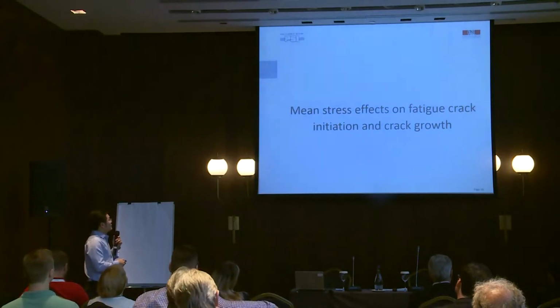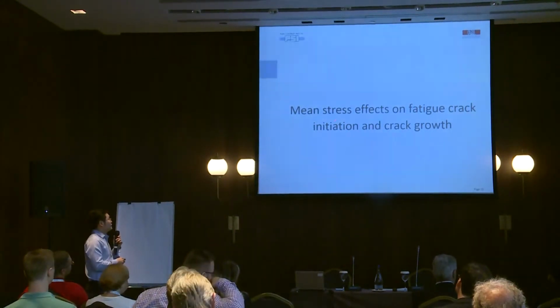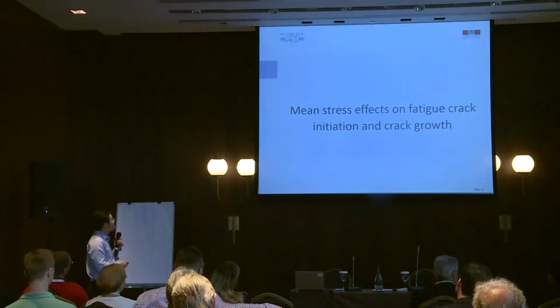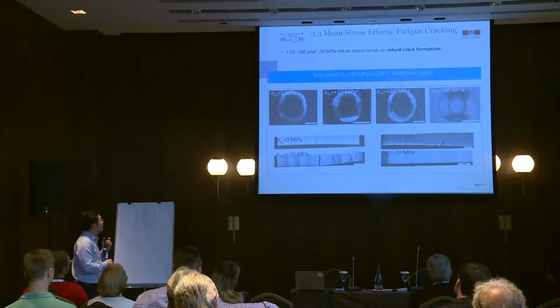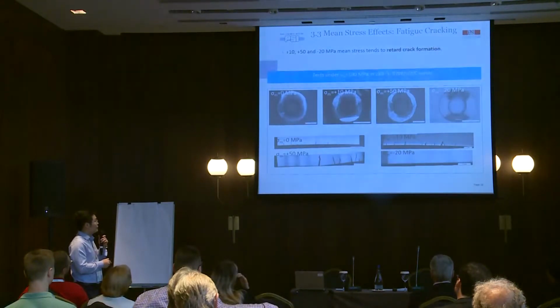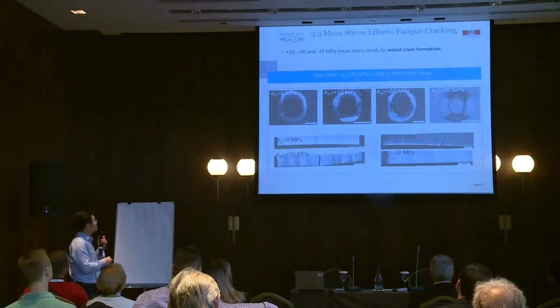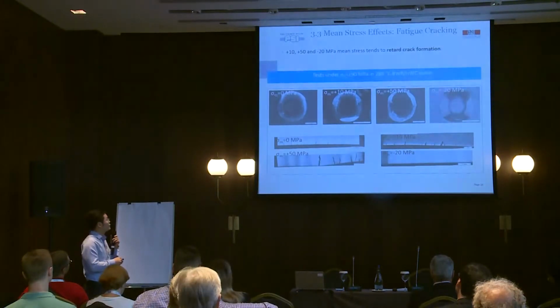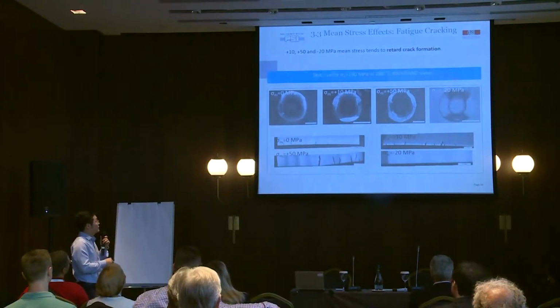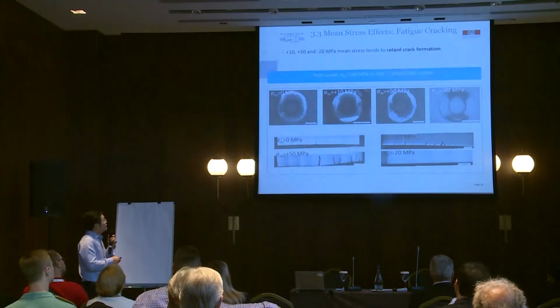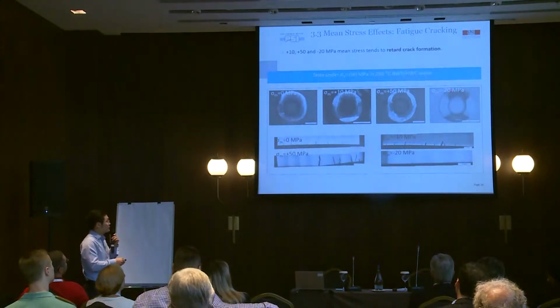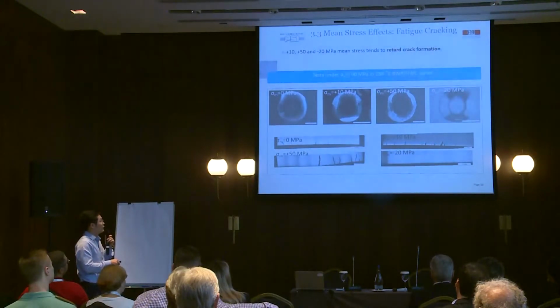And then we studied the mean stress effects on the fatigue crack initiation and crack growth. We took the fracture surface for fractographic investigation. This kind of dark area is because of corrosion in high temperature water, which can represent the fatigue cracking zone. In the dark area, we found that the cracks initiate only from the inner surface at multiple points, except the one with the minus 20 MPa. Only one initiation point was found.